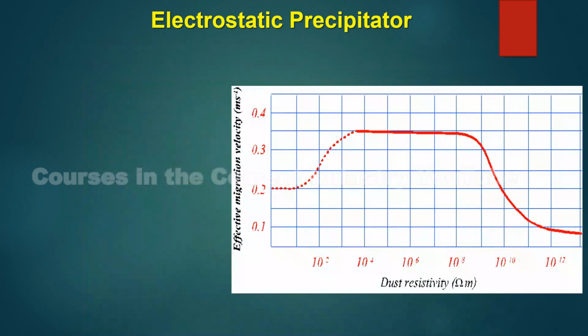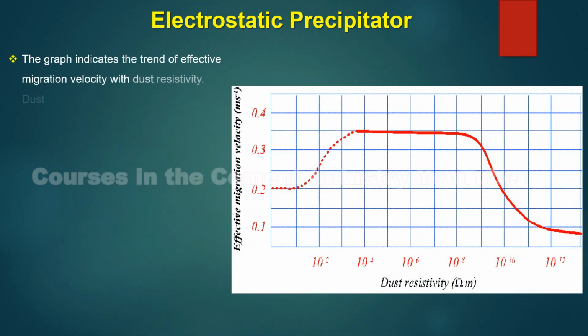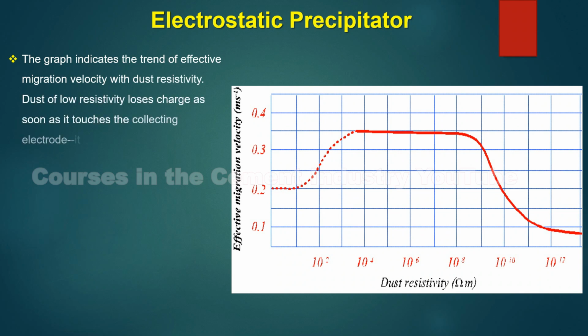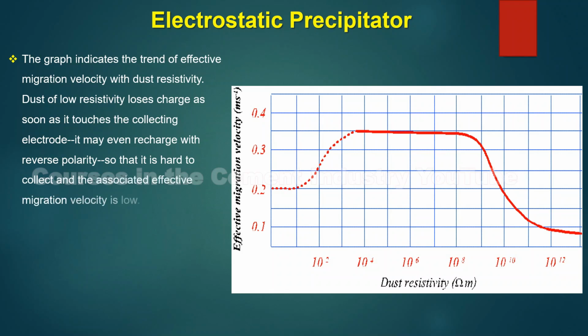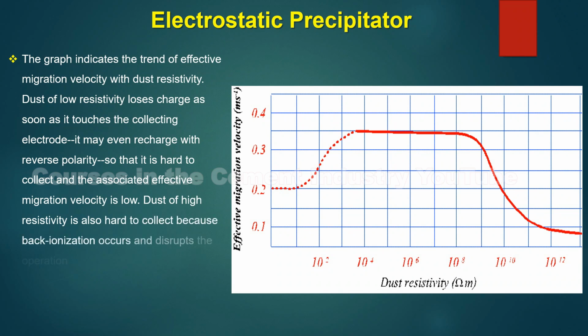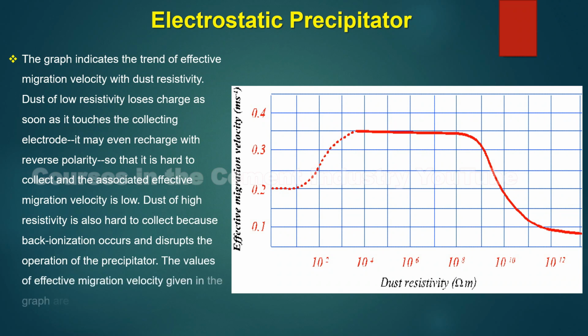The graph indicates the trend of effective migration velocity with dust resistivity. Dust of low resistivity loses charge as soon as it touches the collecting electrode. It may even recharge with reverse polarity, so that it is hard to collect and the associated effective migration velocity is low. Dust of high resistivity is also hard to collect, because back ionization occurs, and disrupts the operation of the precipitator. The values of effective migration velocity, given in the graph, are indicative only.